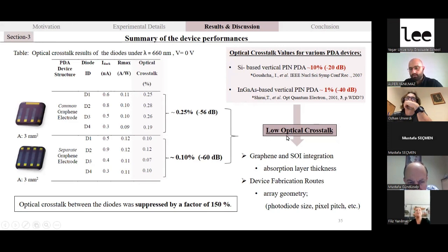This lowest optical crosstalk value is related to the graphene and silicon-on-insulator integration due to the absorption layer thickness, and then the device fabrication routes, because you can change the array geometry, the photodiode size, pixel pitch, etc. By doing so, we can suppress the optical crosstalk between the electrodes.